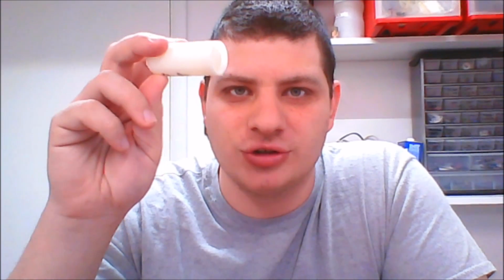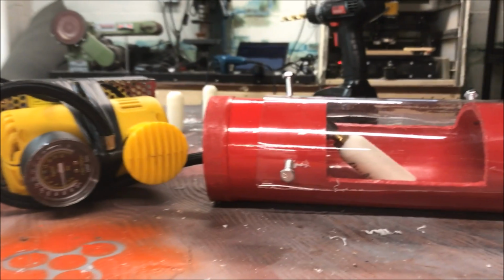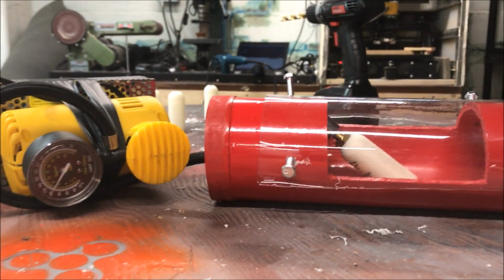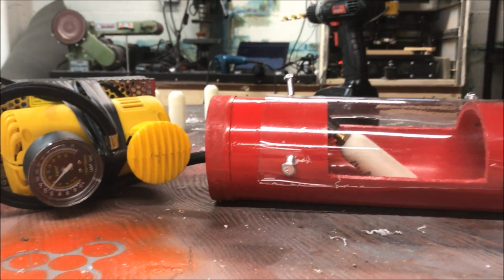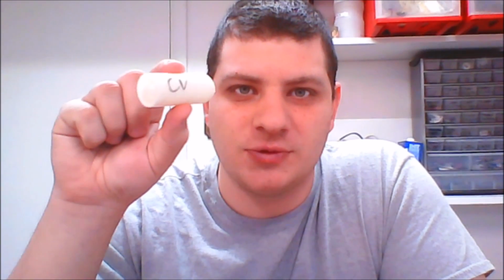First of all, the control still held absolutely zero pressure. This thing was still completely porous. The TPU samples also did not hold any pressure. The slurry, on the other hand, held some pressure. It got up to, it looks like, 100 or 120 PSI. The acetone smoothed, which was my favorite and a lot of people's favorites before I started, also was porous and held zero pressure. But the winner was the resin. The resin smoothed looked like it held 140 or so PSI.